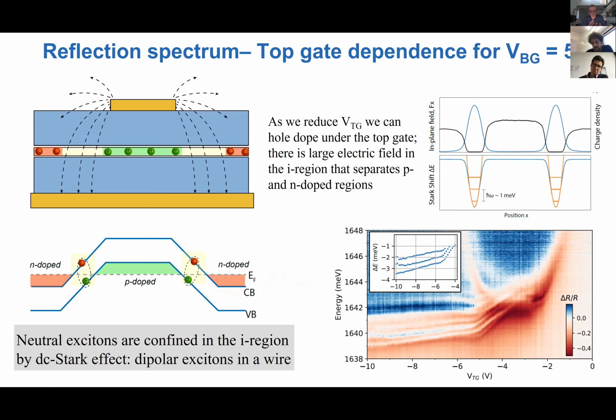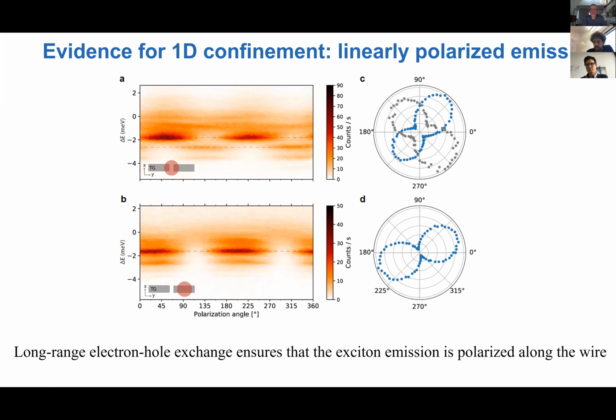Okay, so I find this remarkable because this is a PIN device, right? And it has a very tiny undoped region, and there we have one-dimensional excitons with quantization of their motion along the electric field direction. Now, how do we prove this? We look at the polarization properties, okay? So basically in two different regions. In this case, these gray areas are the top gate voltages. If our focused laser spot is overlapping here, then these lowest energy resonances are all linearly polarized along the same axis. And this is precisely what you expect to see from a 1D emitter due to the electron-hole exchange interaction.